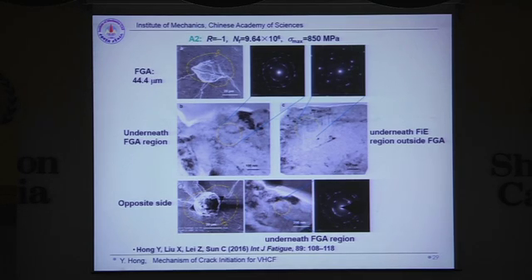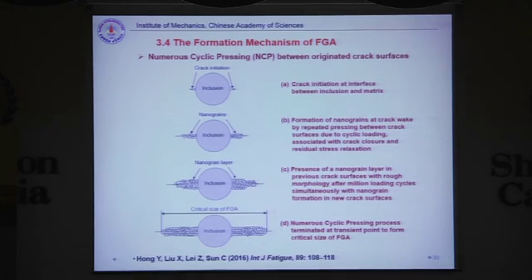So I will say that our observations show that the region of FGA is a kind of fine microstructure. In fact, it's a kind of nanograin layer. But beyond this region, or underneath or outside this region, is a coarse microstructure. Therefore, we propose this kind of model called numerous cyclic pressing, NCP.